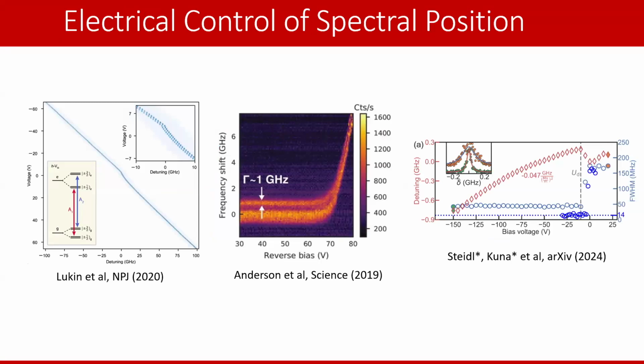So while there are moving charges in silicon carbide that contribute to the spectral diffusion, there has been evidence in both the divacancy and the silicon vacancy that by placing a diode structure around the defect in question, you can put the diode in reverse bias and sweep out the charges using a depletion region in the diode, and this will stabilize the defect's spectral diffusion. You can see this from Chris Anderson in the divacancy, and then more recently from Stuttgart, Timo's work showed that this can be done with a Schottky diode.